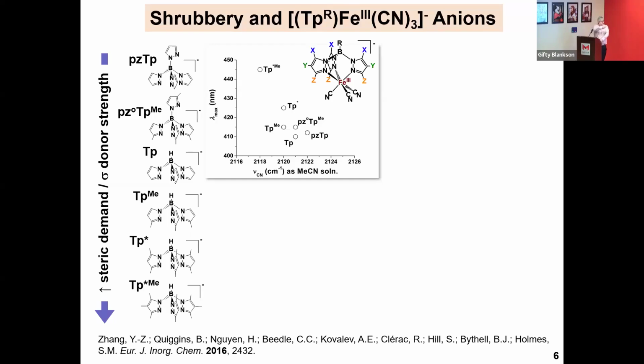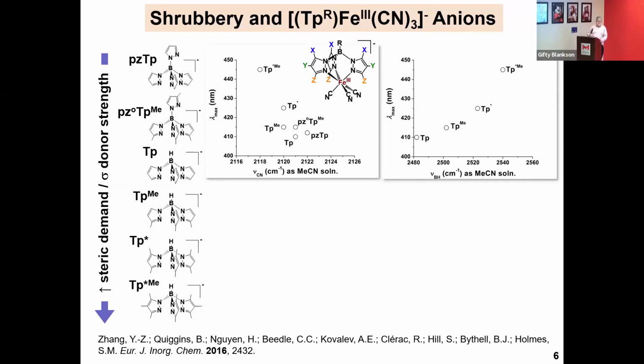Right, and in this axis is just the absorption energy required for charge transfer between the ligand and the metal, so-called ligand to metal charge transfer. These are very dark and intensely colored materials, and it's because of that electronic transition. I'm not going to focus on that. But I will focus on the cyanide and the borohydride stretches because what's counterintuitive is that the most electron donating of the series tend to give BH stretches that go in the opposite direction energy-wise.